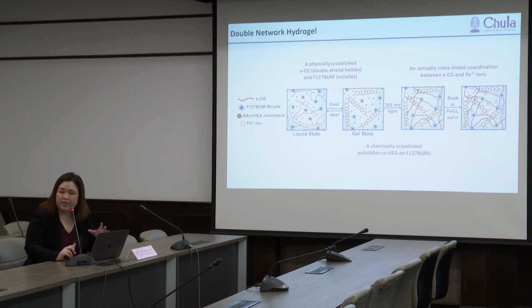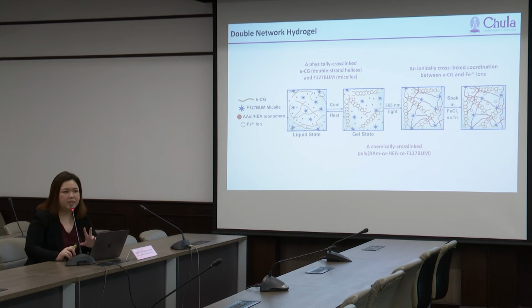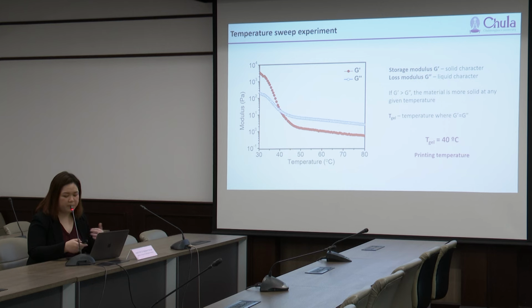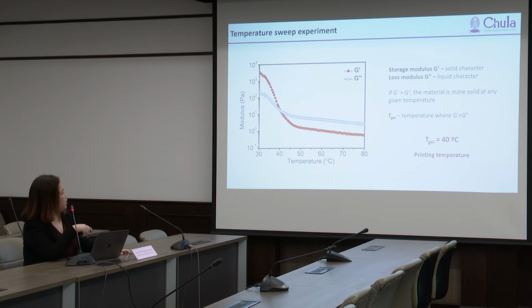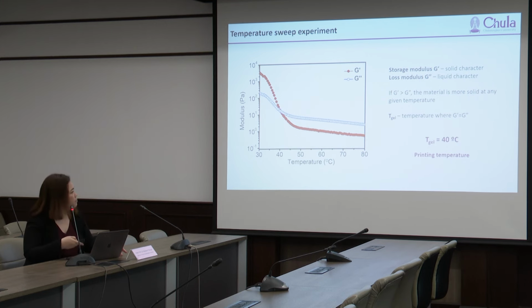So before we can do the 3D print, we need to determine the temperature that we use to print. So we have to perform the temperature sweep experiment, where you plot the modulus versus the temperature. So you can see that at high temperature, the mixture is liquid. But then when you lower the temperature down to 40 degrees Celsius, the mixture becomes a gel. So at this point, it will become a gel. And then we will use 40 degrees Celsius as the printing temperature.